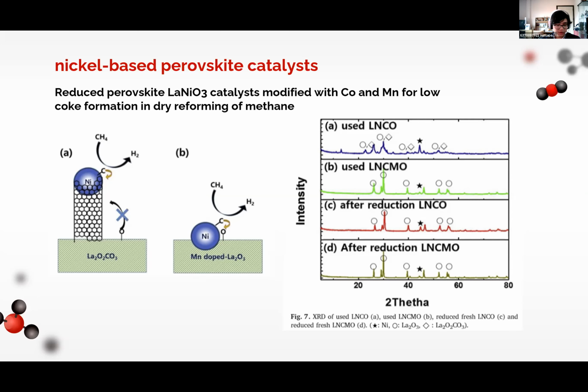This paper shows that using pure lanthanum perovskite will cause carbon growth, and when regenerating the catalyst it lost some active sites. From the experiments, manganese addition reduces coke formation and makes it easier for the oxygen from lanthanum oxide perovskite to react with the carbon on the active site, so that when regenerating, the active site is not lost.